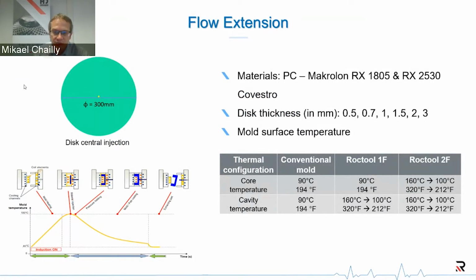So if we take a look at this first study of flow extension, we consider a central disk of 300 millimeter diameter with a central injection, and we inject two different materials, two of them being Makrolon grade from Covestro that are used in the medical industry. We tested different disc thicknesses ranging from 0.5 up to 3 millimeters.